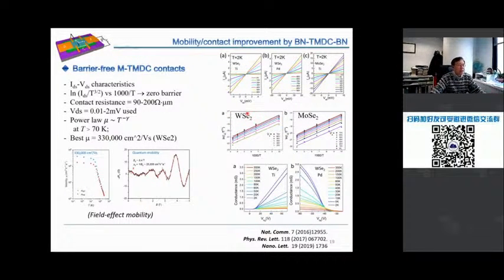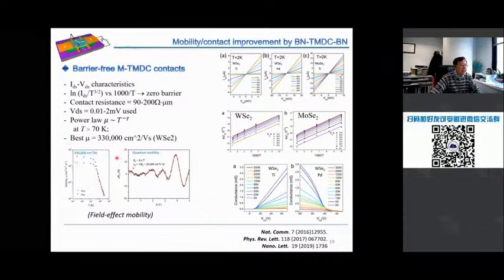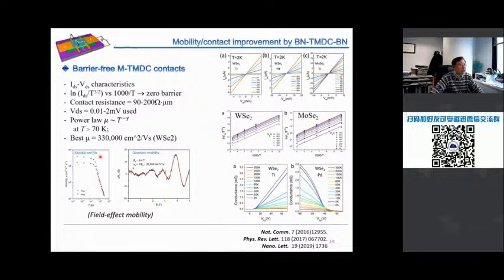the transport properties. Is this a good ohmic contact? Yes, we measured different materials, for N-type and P-type. So you see pretty nice curves on the on and off. And importantly, the mobility that we can achieve in these WSe2 structures is about 300,000. That mobility is already comparable to that of high quality graphene, right? And you see nice quantum oscillations. The quantum mobility is also very high.